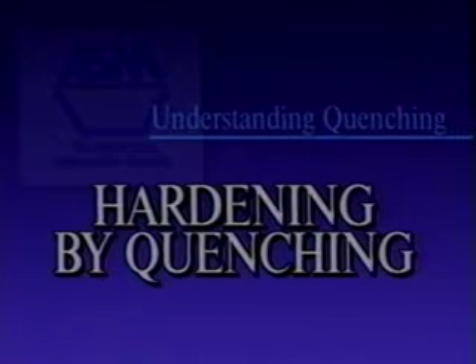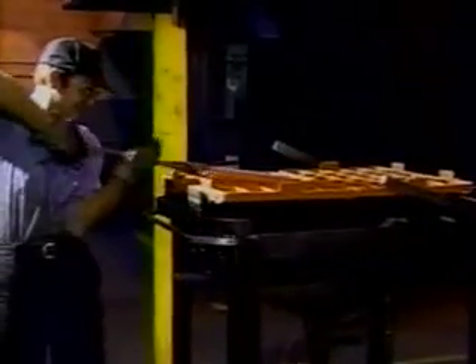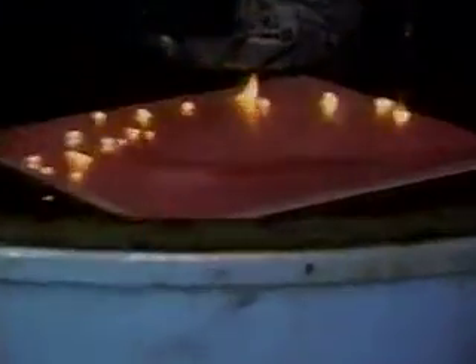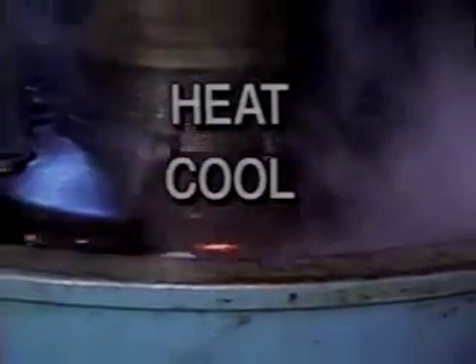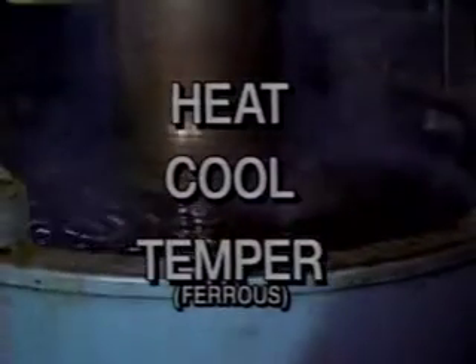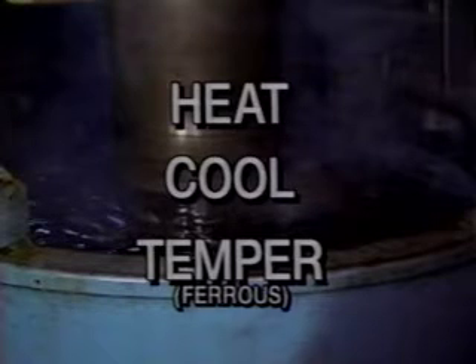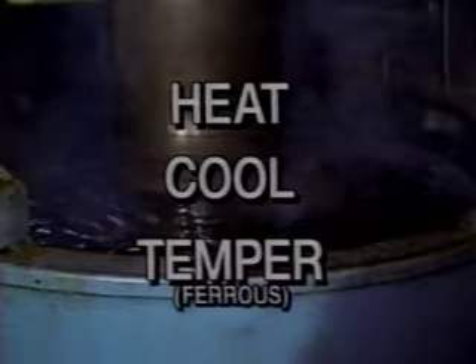Hardening by quenching. In the heat treating facilities where ferrous alloys are processed, the primary purpose of quenching is to harden. The materials treated are usually the carbon steels, the low and medium alloy steels, and tool steels. These materials are heated to high temperatures, then quenched. Typically, the quenching process is followed by tempering, which involves heating and then cooling again. Tempering is done to reduce the brittleness that rapid quenching produces in steels.